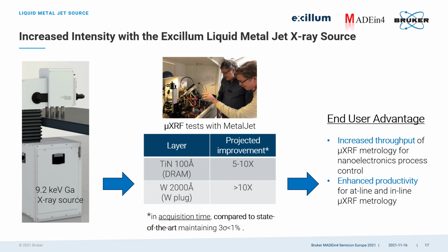Two sample types were measured that are relevant to semiconductor processes, namely thin titanium nitride and thick tungsten. First results showed a 5 to 10 times improvement in detected flux compared to the common solid anode microfocus tubes. Such boosted flux will increase the throughput of the micro-XRF measurements in the process and is eventually beneficial to the end customer who experiences an enhanced productivity.